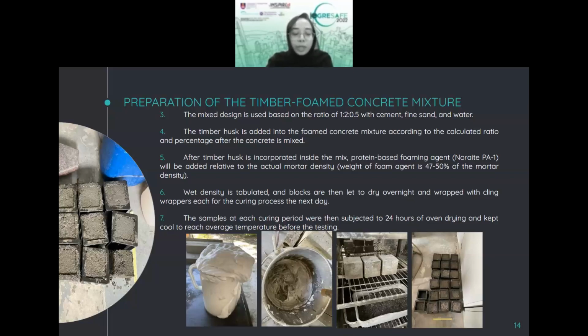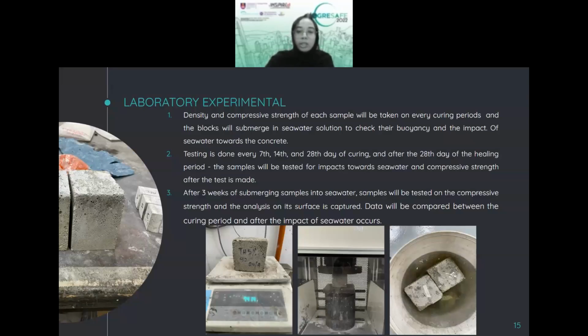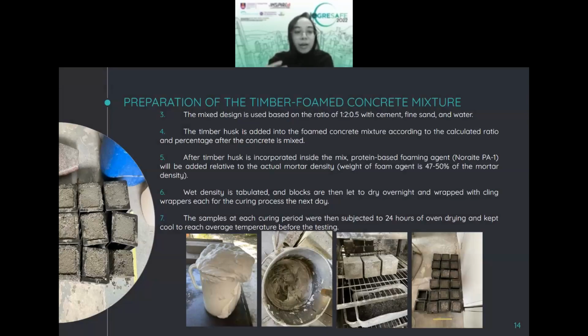And it is then incorporated inside the mixture as the protein-based foaming agent, where for this mixture, I will use a weight of foam agent of around 47 to 50% of the mortar density. So before that, I have to calculate the wet density and everything. After I finish with the mixture, I will recalculate the wet density and will tabulate the wet density of the foam concrete. And afterwards, each block is then left to dry overnight and wrapped with cling wrap to start the curing process itself. So after that, when coming to testing the sample, each block will be subjected to 24 hours of oven drying and kept cool to reach the average temperature before the testing started.